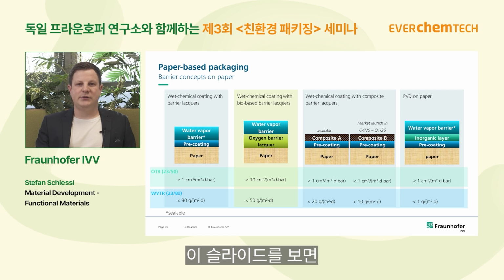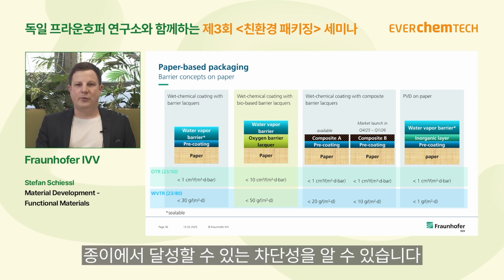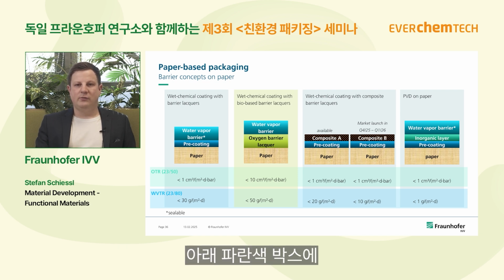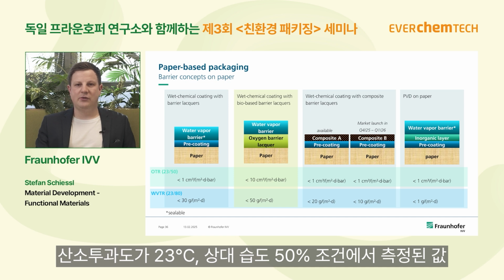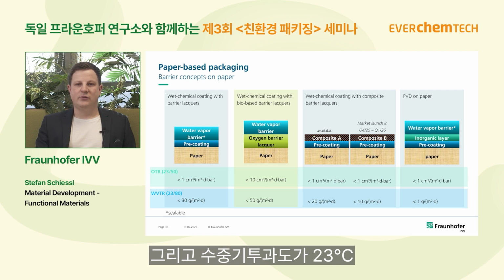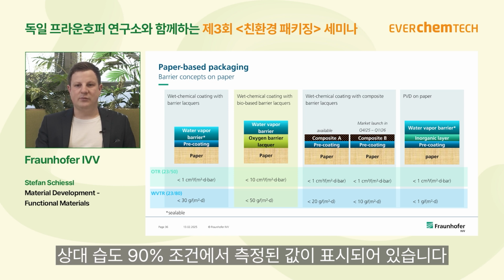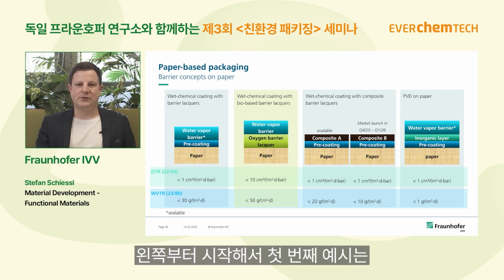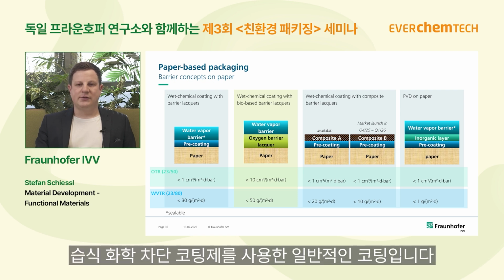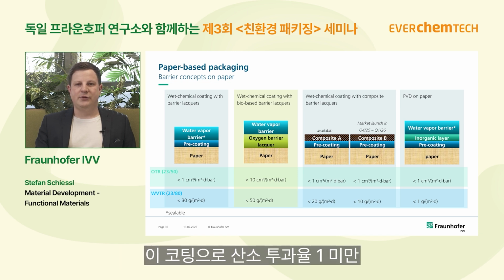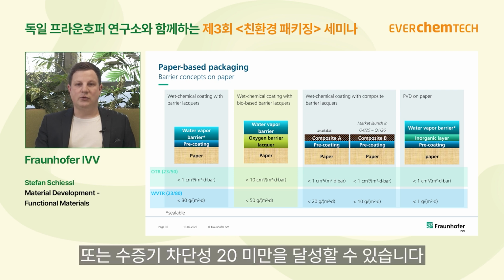Here on this slide you see a summary of the barrier properties that are possible to achieve on paper. You see the OTR value measured at the conditions 23 degrees Celsius and 50% relative humidity, and you see the water vapor transmission values measured at 23 degrees Celsius and 90% relative humidity on the blue box below. So starting from the left side, this is a typical coating with a wet chemical barrier lacquer. Here we are able to achieve oxygen transmission values below 1 or water vapor barriers below 20.